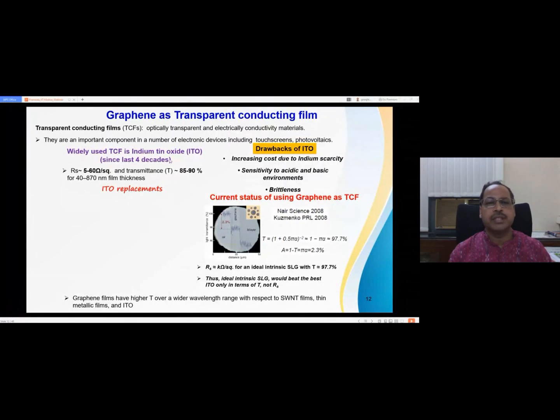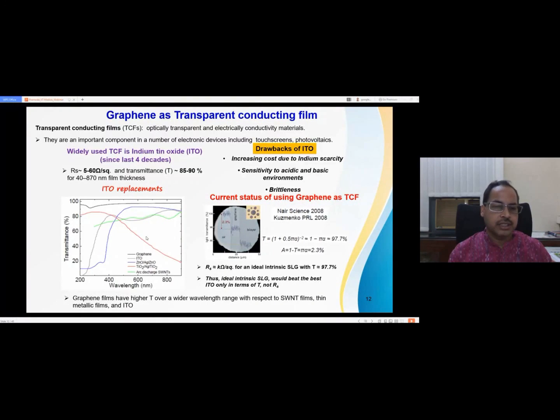For the last 4 decades people have been using indium tin oxide. The disadvantage is increasing cost due to indium scarcity, and it is sensitive to acidic and basic environments, and it is brittle. It will break. So there are several researchers finding ways to replace ITO. This curve shows different materials like ITO, zinc oxide, carbon, single wall carbon nanotube, but you can see graphene has the advantage. Graphene films have higher transmittance over a wide wavelength range. But what happens? Because here is the famous Science paper by Nair et al. In 2008, one layer graphene film will transmit 97.7%. So transmittance is very high.